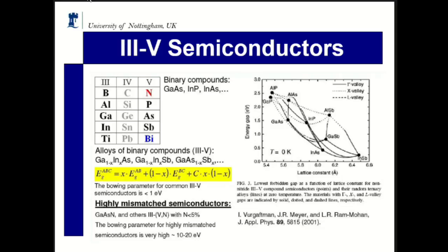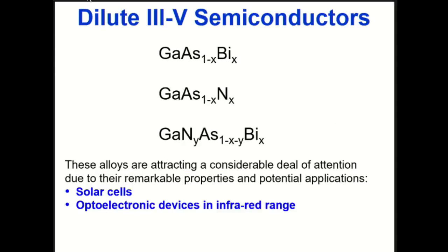But there was another idea as well, how to replace a smaller atom, arsenic, by a bigger atom, which is bismuth. So now you do the same thing. This is what we call dilute nitrogen or bismuth. You're just replacing that arsenic atom by either nitrogen, which is smaller, or by bismuth, which is bigger, in order to reach this 1 electron volt material system without actually changing the properties or the size of that crystal in order to match the other one. And that's what we can have, this combination.